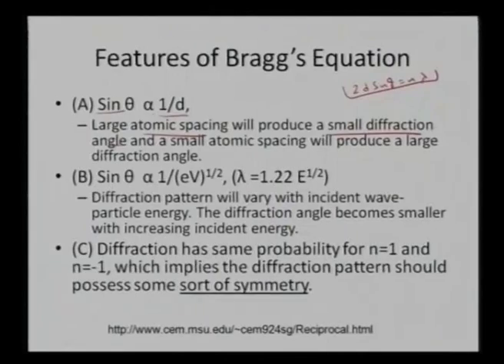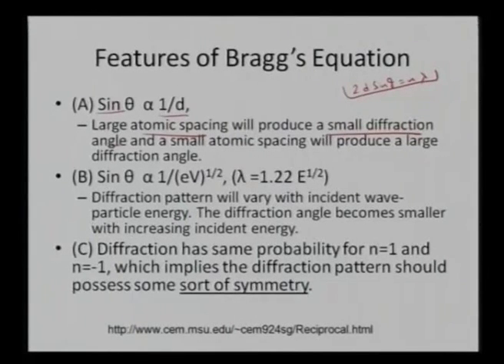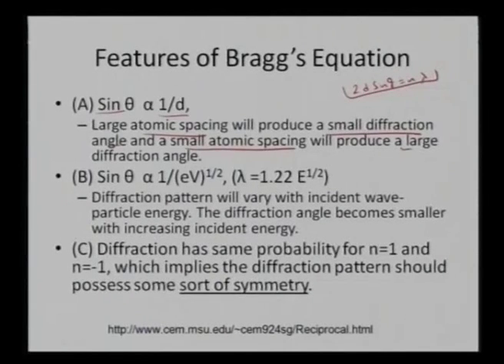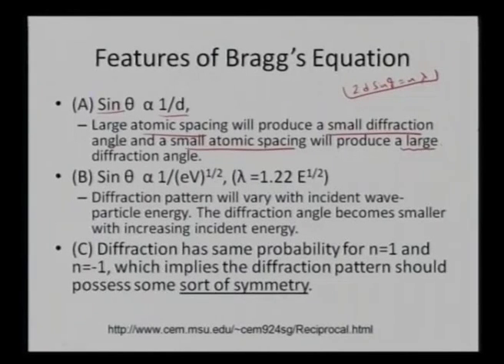As lattice spacing increases, I get diffraction at much smaller angles, and smaller atomic spacing produces a larger diffraction angle. That is the inverse relationship between interplanar spacing and diffraction angle.